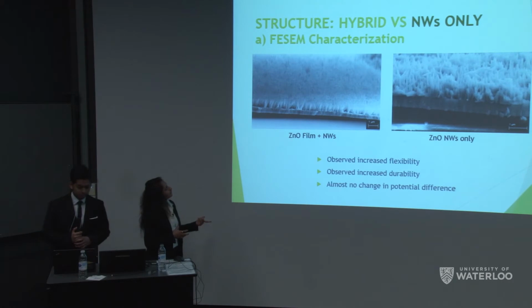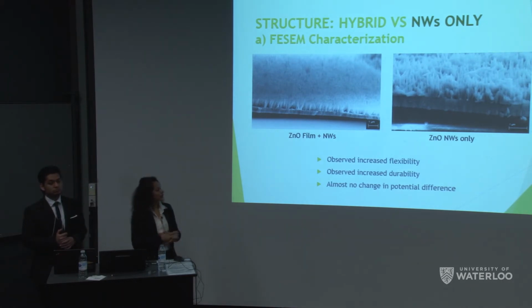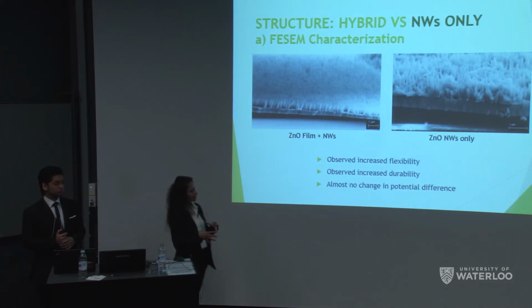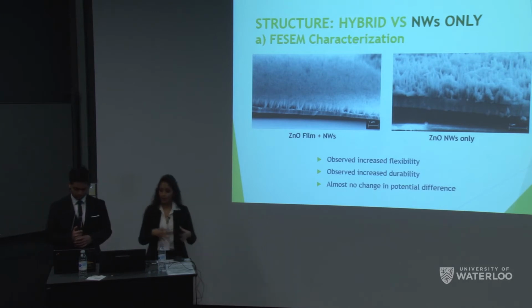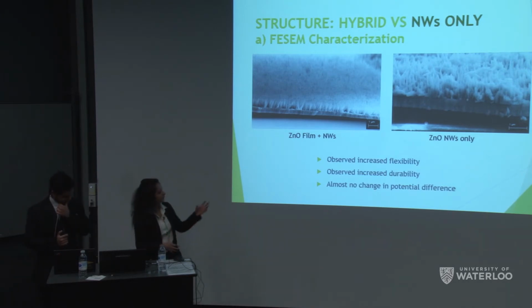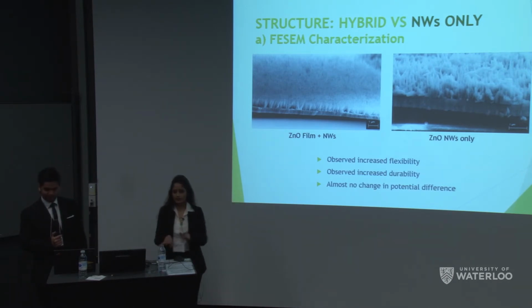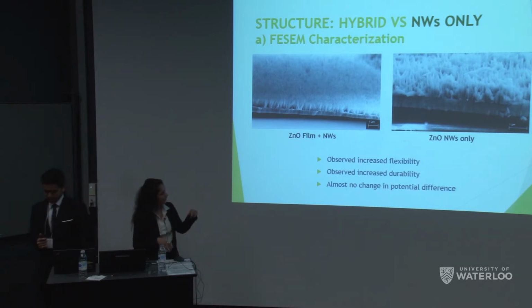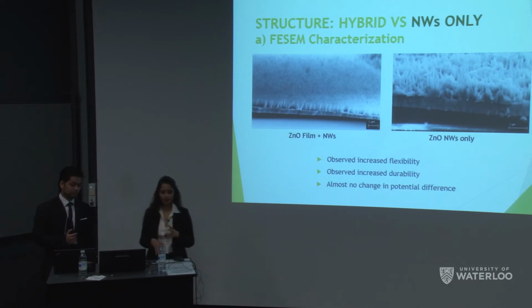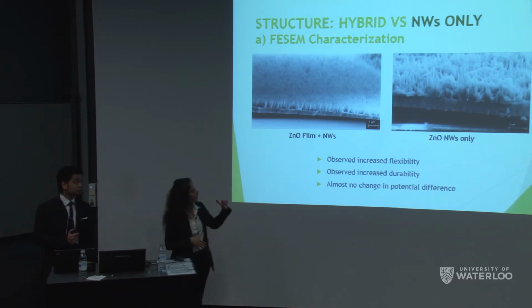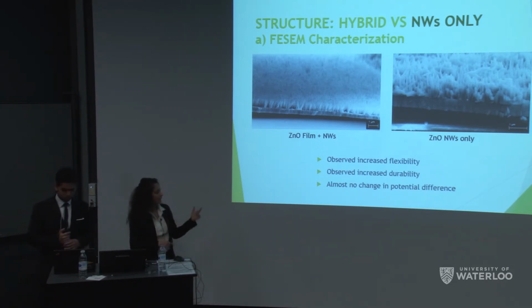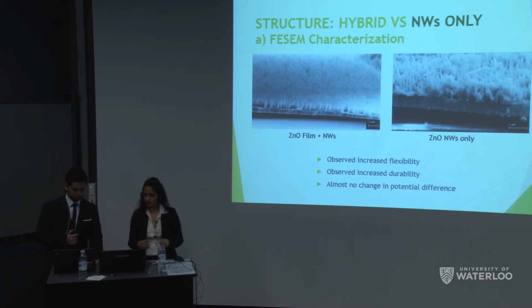And the third factor that we considered was the structure. So we wanted to see whether a hybrid device would give us more output and more durability of the device, or just nanowires. So we considered that as well. We went and we made both. But with testing and with working with the device, we observed that the zinc oxide nanowires device only gave us increased flexibility and durability, and there was almost no difference in the output that we got for both the devices.